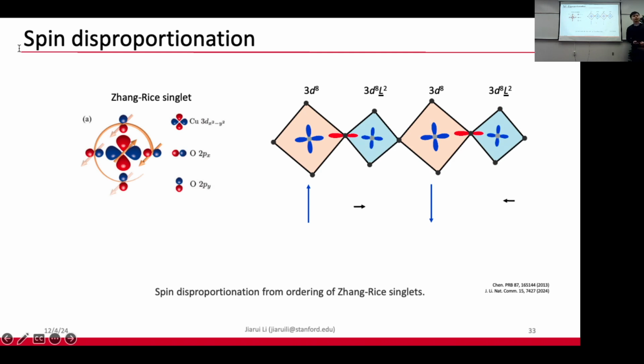In principle, yes, but currently the limitation is that this structural distortion is happening on the oxygen atoms only, and in regular X-ray diffraction, oxygen doesn't contribute too much because it only has 8 electrons, so the oxygen intensity is very low. Even in neutron or electron diffraction, people don't pick this up that much. One idea is that you can use resonance with oxygen, but the oxygen edge is at 520 electron volts, and the range in momentum space is not long enough for us to reach that Bragg peak. Okay. Yeah. Thanks.